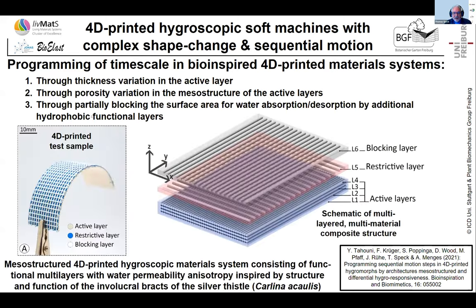And by doing this, we had a structure which looks like that. Here we have, in this example, 4 actuating layers, 1 restricting layer, and 1 blocking layer. And by printing this, we can orchestrate a motion sequence. So the mesostructure of this hygroscopic material consists of functional multilayers, which have an anisotropy in water permeability, and this allows us to orchestrate the motion of a system like silver thistle did. And at the end, we built a very simple soft machine by this approach.